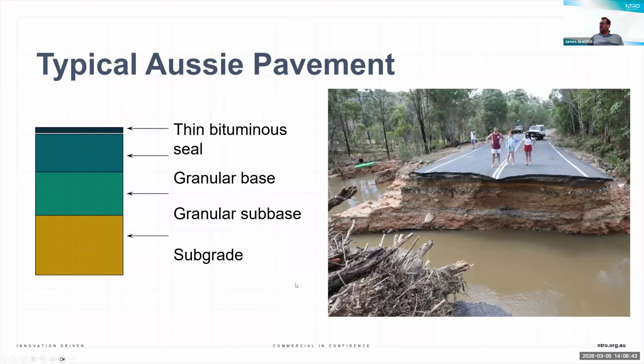Here's a typical Aussie pavement with some typical Aussies, local people having a look at whether they're going for a swim or not. But typically we're talking about a thin bituminous seal on top of a granular base, which is over a granular subbase and subgrade material. I've managed to ruin the formatting slightly, but I should have noticed that before. And on the right-hand side is showing conveniently a typical pavement cross-section. This one actually looks like maybe it's a thin asphalt surfacing as opposed to a sprayed seal. But essentially a nice unbound granular pavement that then, due to a weather event, has essentially been washed away. So these are some of the issues that we're facing in Australia.